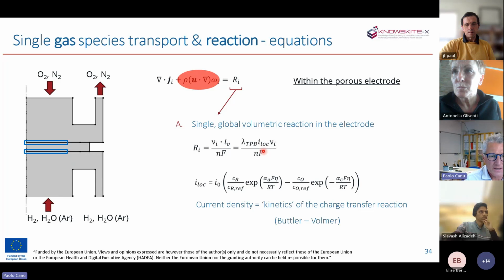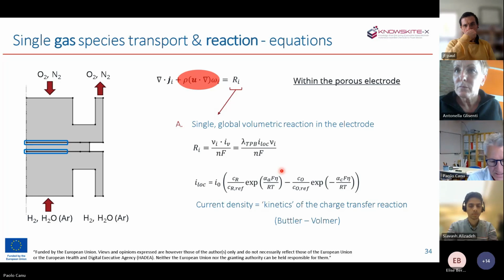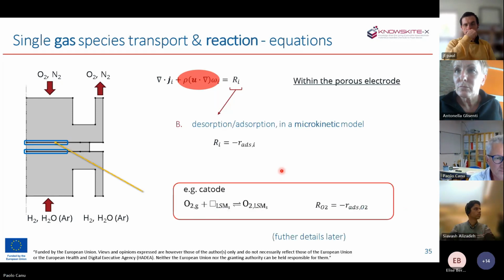Typically this current density at the triple phase boundary is described by a Butler-Volmer expression that is semi-empirical, but is essentially based on the assumption that the whole electrochemical process can be described by a single reaction. And by the way, it also somehow hides the idea that the rate-determining step is the charge transfer reaction.